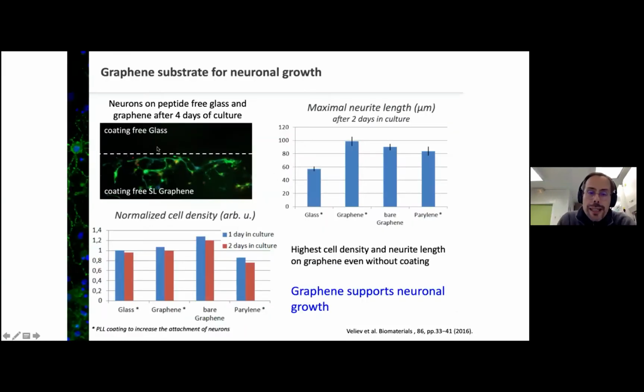And during that study, we found that graphene was indeed promoting the growth instead of just letting the growth. So we see that the neurite length was higher than expected and higher than other materials. And not only the neurite length, but also the normalized cell density. So we got not only biocompatibility, but biostimulation by graphene.